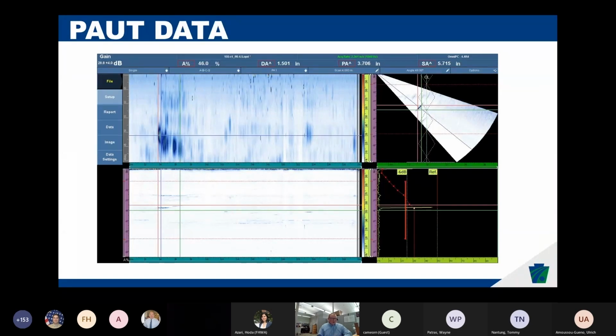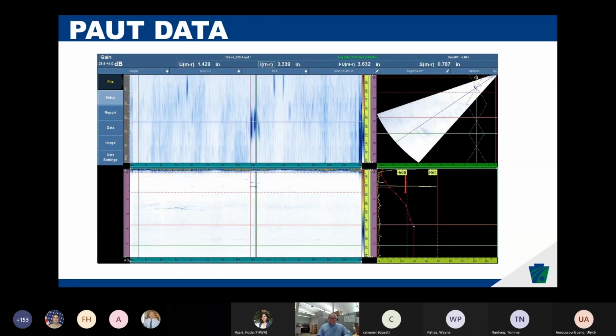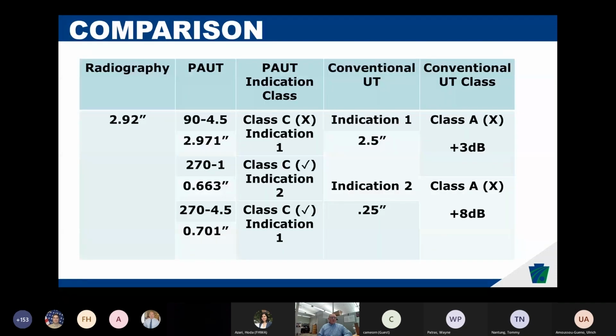Looking at the data, obviously it found the radiographic 3-inch flaw to the left in that little interval, but it also found this other flaw out here in the middle of the joint that radiography just didn't pick up or couldn't find. Looking at the one that the radiograph actually found, and we also used some conventional ultrasonic testing in this case, the phased array was very comparable in size. Maybe the indication was a little bit closer to the film in this case. It was a little bit lower in height with respect to that joint. So, a pretty good comparison of what they can and can't find.